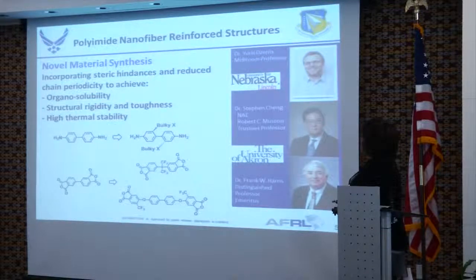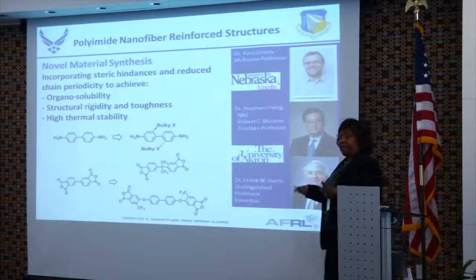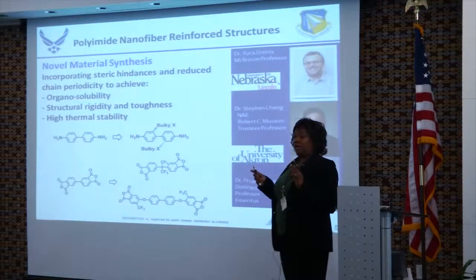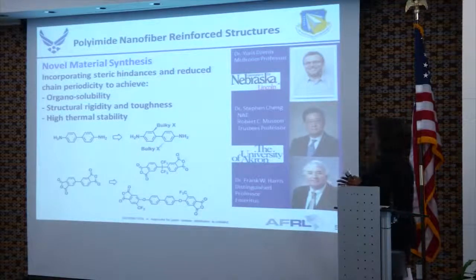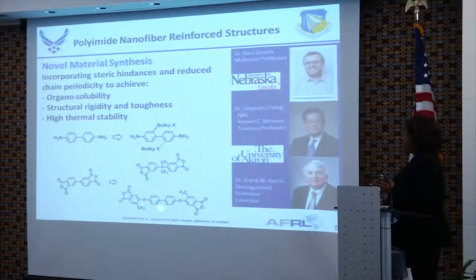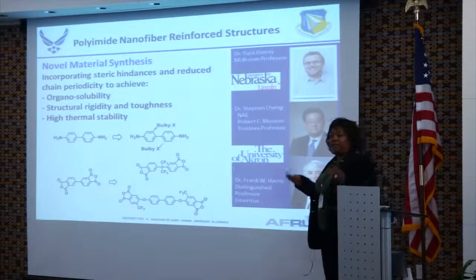So what this team has done, the synthetic expertise here, is look at polyimide chemistry and make new polymers, novel material systems, looking at new compositions of matter in terms of diamines and dianhydrides, and incorporating the right functionalities into these monomers to get the properties you ultimately need to process these materials. So they're incorporating bulky, sterically hindering groups, incorporating kink linkages into the backbone chemistry, in this case in the diamine, and doing copolymerizations to reduce the periodicity in the structure.